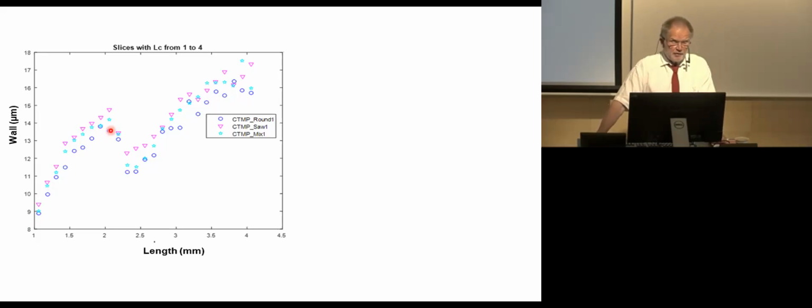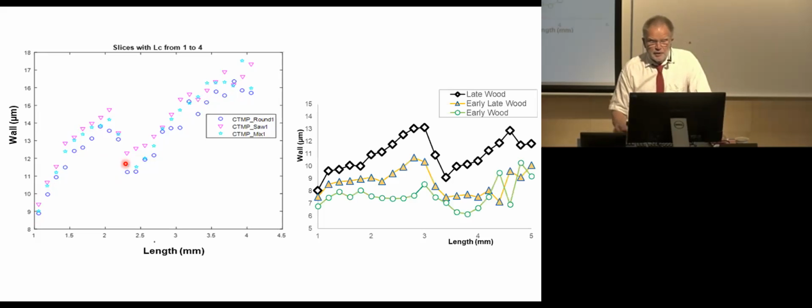Furthermore, what you can see, which is impossible with averages, is you have a dip here. We just happen to see it. We don't understand why it is like that. But then we thought, if we cut the wood into early wood and summer wood particles, late wood, those are the thick-walled fibers, and the early wood, those are the thin-walled fibers, and then the natural mixture here. We dissolved it and ran it through the analyzer. And even in the raw material, you have this characteristic dip, which I have no idea why it is like that. That's ongoing studies.